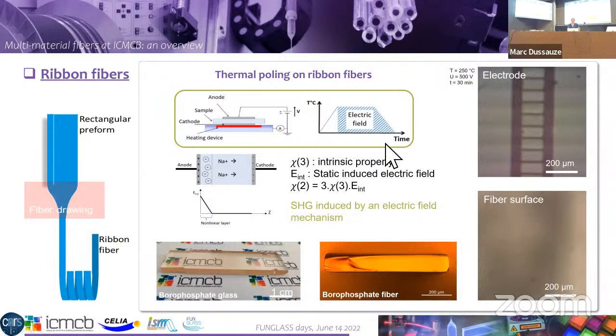So here is the quick scheme of the system. We apply a voltage to the materials while we heat them at the same time, generating some diffusion of sodium. We break the symmetry of the materials. So this is roughly the method, but I would say that before applying the poling on these materials, the first challenge was to make the fibers.